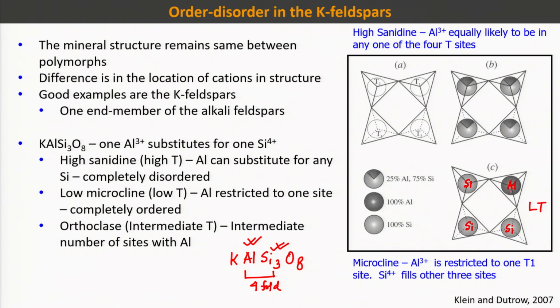Because in this site aluminum will go, because very close to this you have some potassium. So, because of that the exchange reaction will be balanced. So, it has a 3 plus and it has a plus 1. So, it will make some kind of solid solution. So, because of this, at this particular site aluminum will fit, but at high temperature any of these 4 asymmetric tetrahedral sites, this aluminum can go. So, aluminum can go here, here, here, here. So, the probability to have aluminum in these 4 different tetrahedral sites at high temperature is 25%. Okay. Here in low temperature, there is 100% probability to have aluminum at this particular site. Okay.